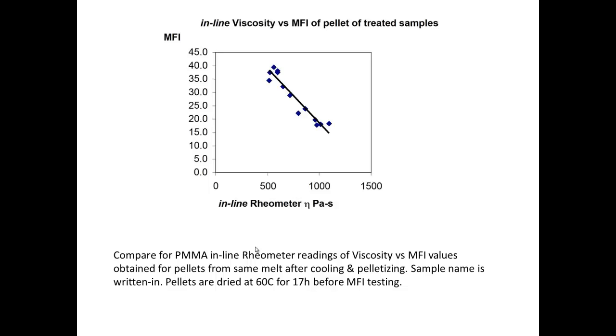What I show here is a comparison, for PMMA, of inline rheometer readings of viscosity versus the MFI, melt flow index, values obtained for pellets from the same melt after cooling and pelletizing. So basically what it says is that the pellets have captured the viscosity drop which is observed in the inline rheometer, and that I can create